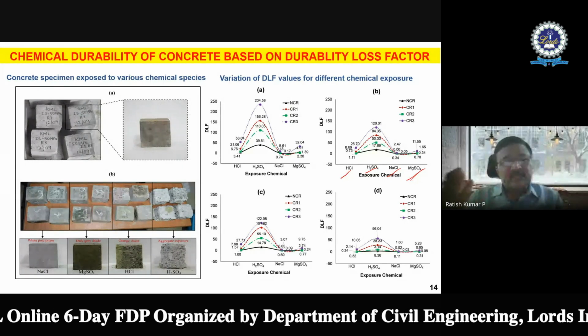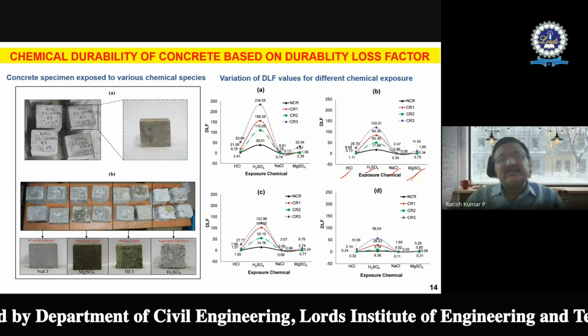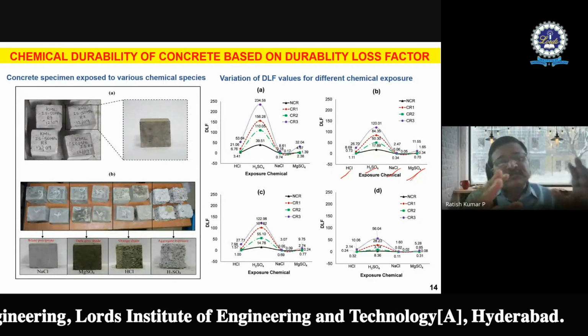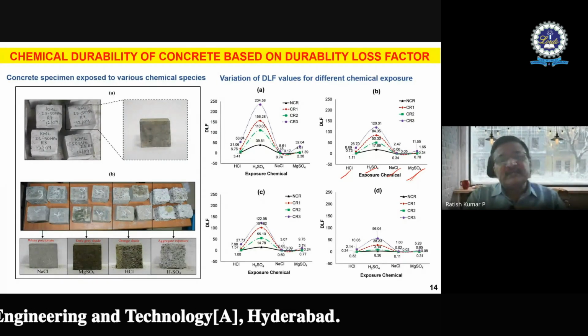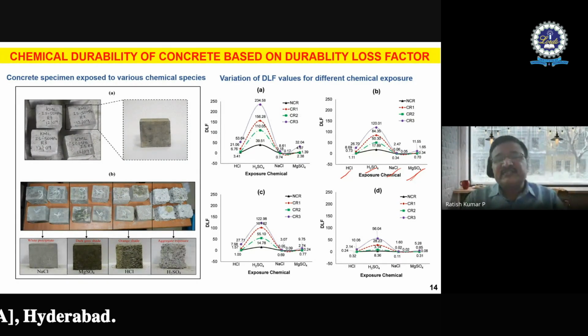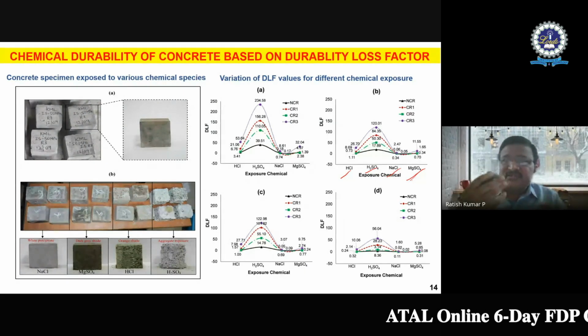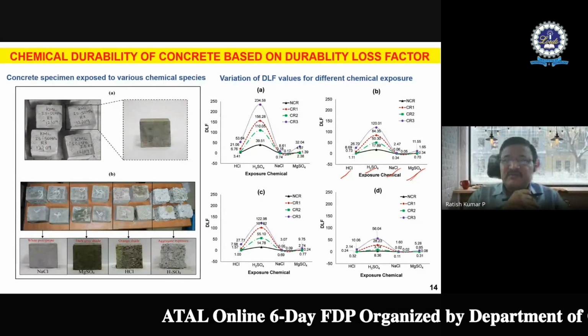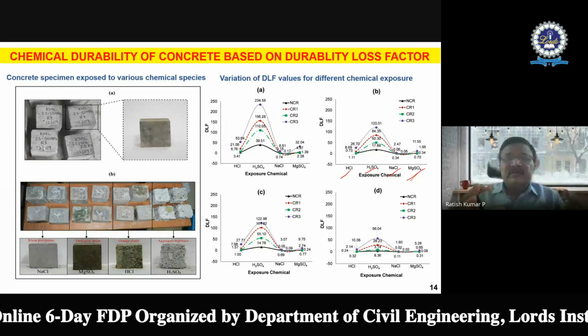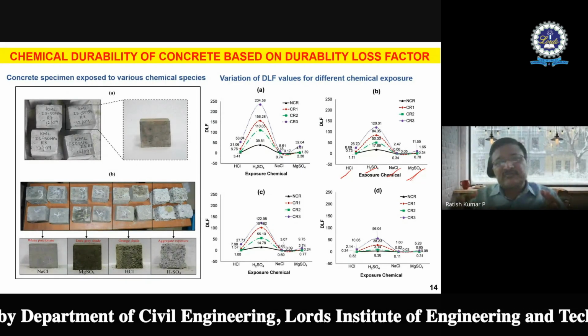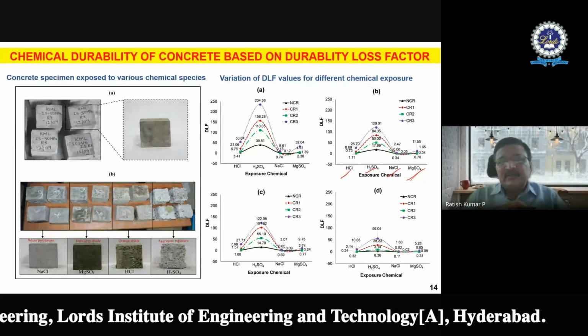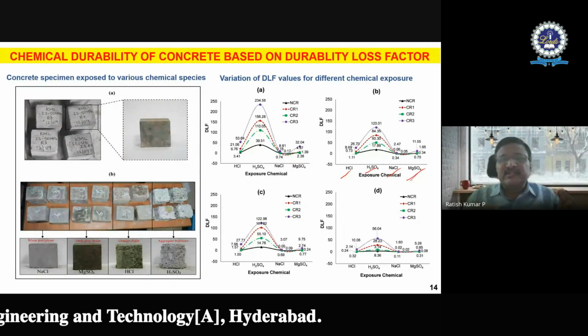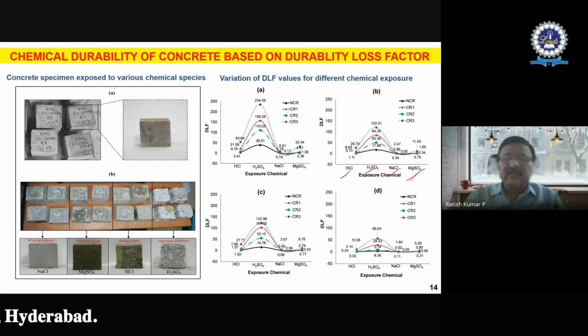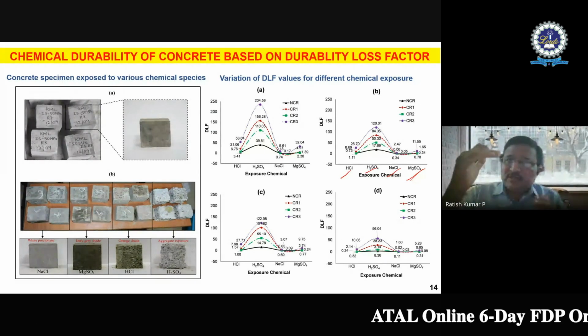When I subject the specimens to different species like this, I calculate four different parameters. One I call the acid attacking factor: when I soak these specimens in different species like HCl, H2SO4, NaCl, MgSO4, it is the change in dimensional stability, the dimension of the structure. Then there is a loss of mass, which I call the acid mass loss factor. And there is a loss of strength at the end of 7 days and 28 days of soaking the specimens in the species I mentioned. Obviously, there is going to be a loss in strength also.